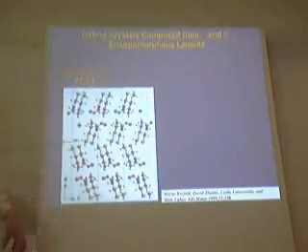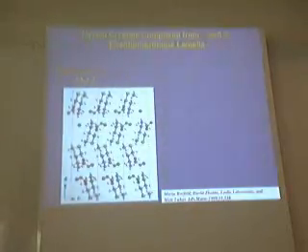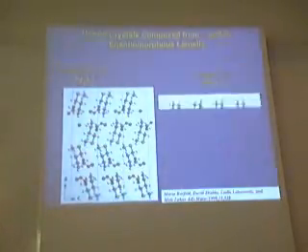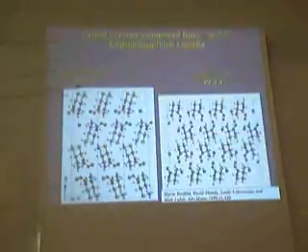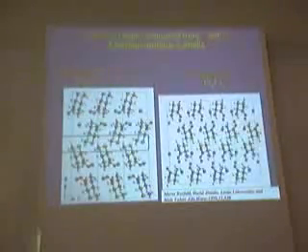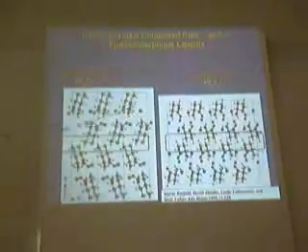As one crystal starts growing, one lamella starts growing, and if one enriches the solution with the other enantiomer, then these faces can operate as templates for the deposition of the other one. And therefore we are actually generating these lamellar twins. This is the same case with cysteine hydrochloride, and we have valine hydrochloride. But now, these are the weak interactions here.